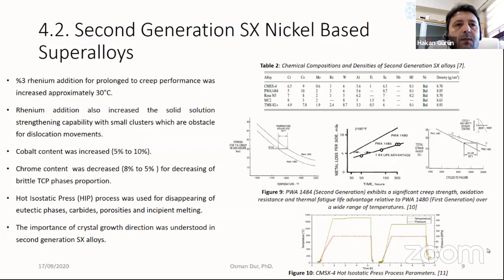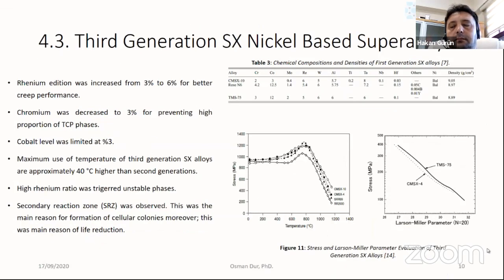In literature, 001, 111 and 011 direction crystal growth were compared. As you see in figure 9, PWA 1484 is better for life and creep than PWA 1480. PWA 1484 is a second generation alloy. In third generation, rhenium addition was increased from 3% to 6% for better creep performance.